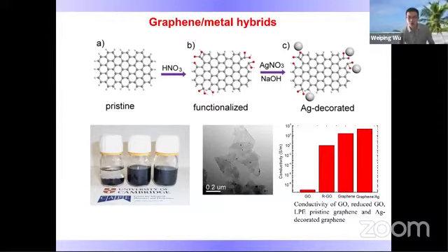I have been using in situ chemical reduction processes and attaching silver nanoparticles on top of the graphene flakes. Therefore, the defects at the edges can be repaired, and these metallic nanoparticles can form interconnections or bridges between the flakes, so that the conductivity can be greatly enhanced.